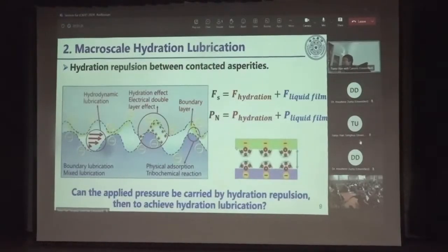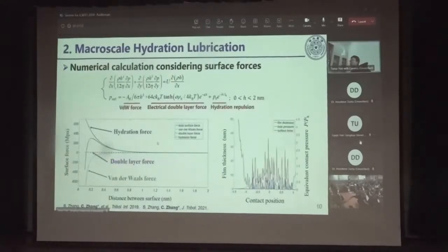Then we proposed a method to form a hydration layer on the asperities surface, and this hydration layer can separate the asperities by the hydration effect, by the hydration repulsion. Then the shear resistance should be reduced greatly. So first we make a calculation, and we should prove whether it is possible to separate the asperities by hydration